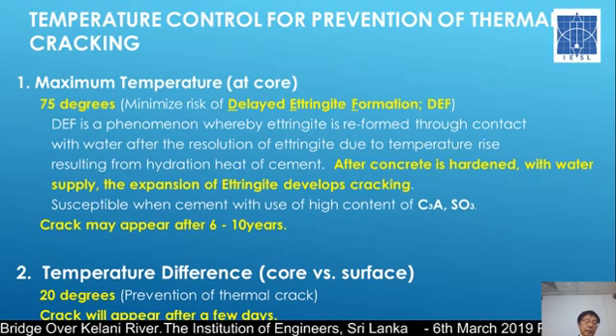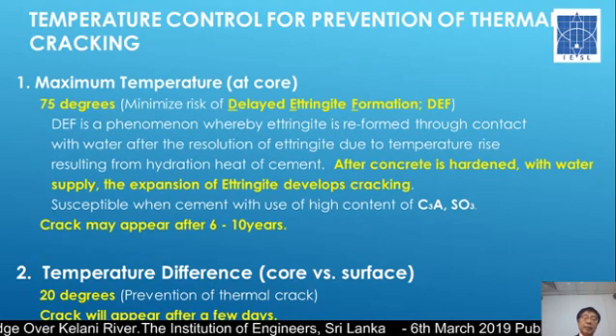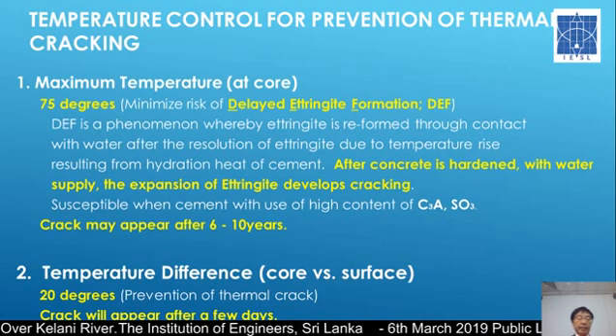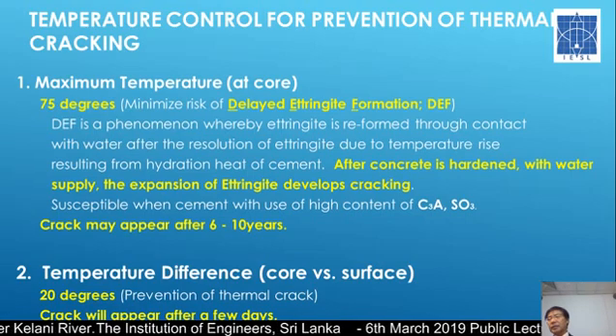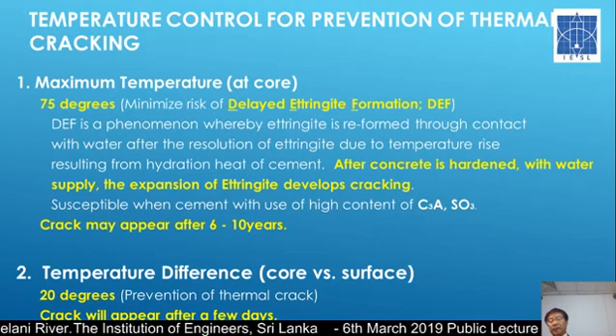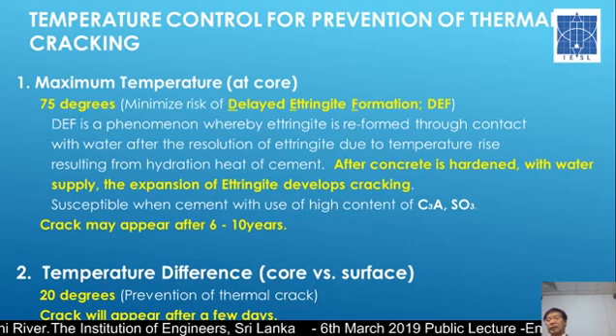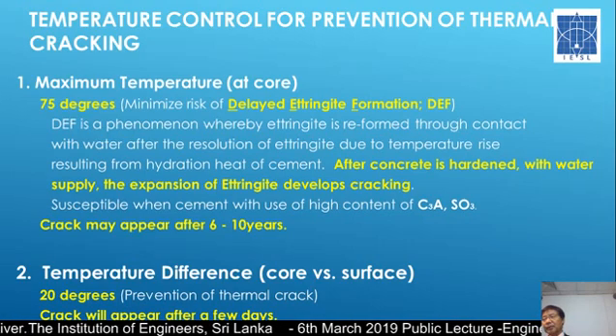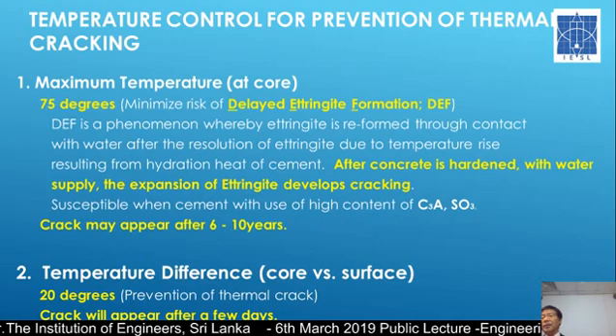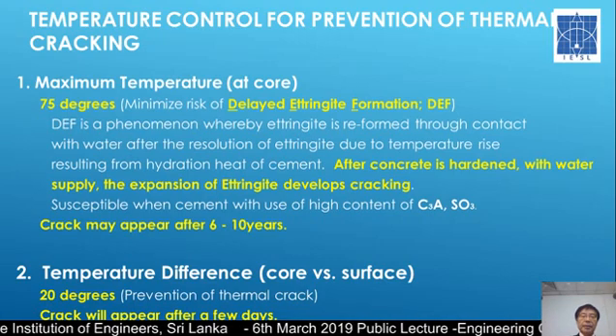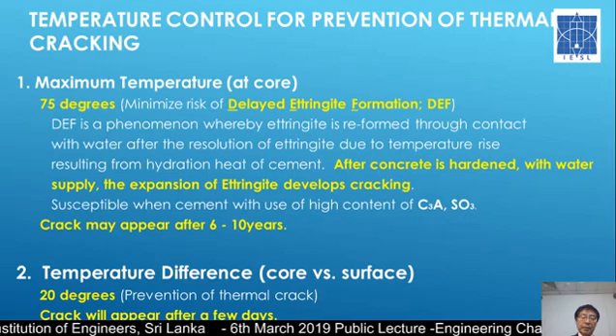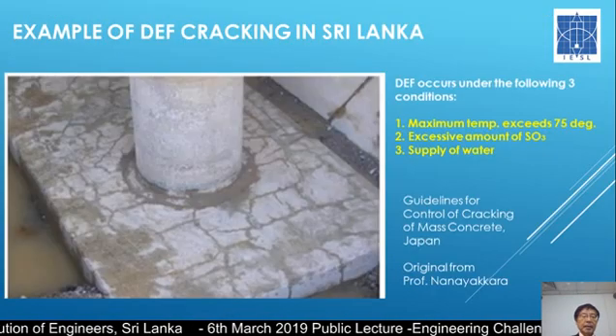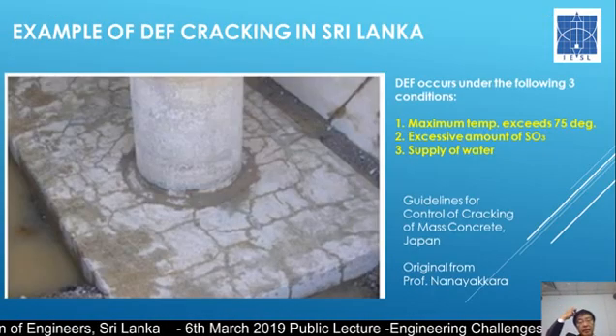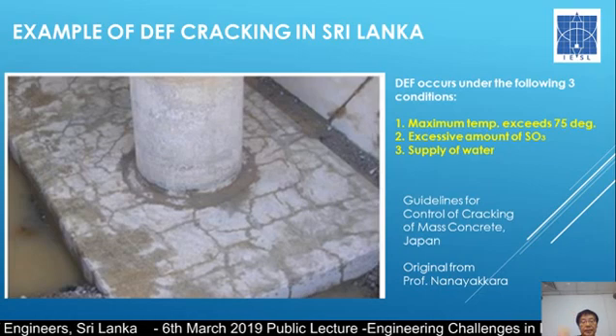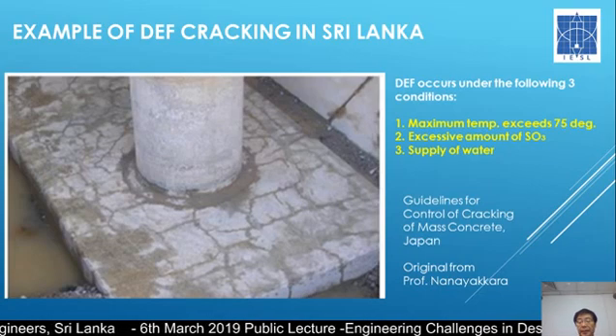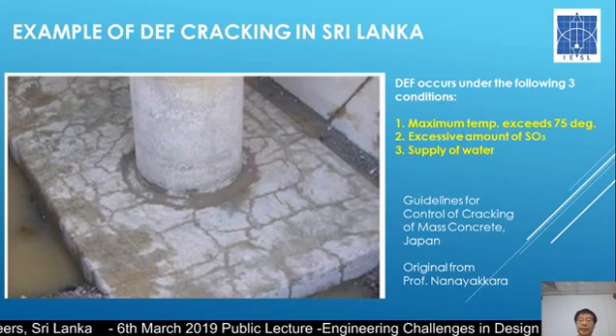So we control the temperature, 20 degrees difference between. However, this cracking only occurs after a few days after casting, because the temperature difference will diminish after a few days. So this is easy, not much difficult to control. So this is DEF cracking, and this is the photo taken by Professor Nanayakkara.